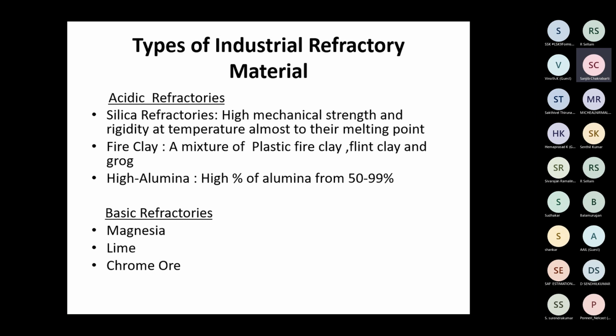Acidic refractory material is different. You can have silica, you can have fire clay, you can have high alumina. Your normal alumina bricks are neutral bricks, but high alumina bricks are acidic bricks. High alumina bricks are huge costly bricks, and they can take quite a high temperature. They can resist high temperature with 50 to 99% alumina.